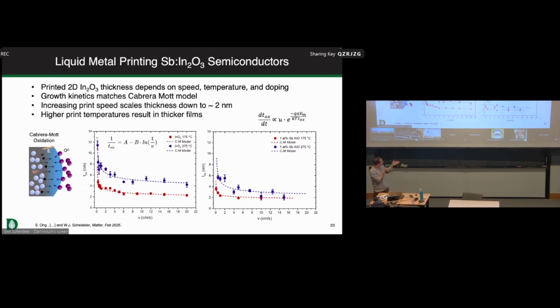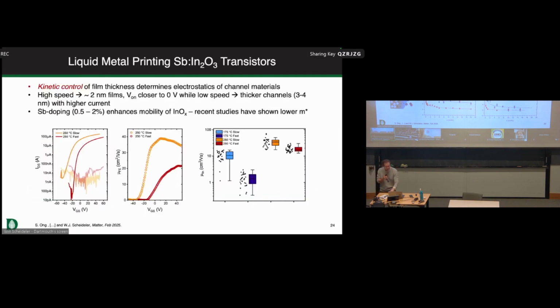So at the smallest scale, when we introduce a dopant like antimony, we can control it down to the 1 to 2 nanometer scale. Now, antimony is an interesting choice. It turns out that unlike a lot of other dopants like tin and gallium, antimony can actually enhance the mobility and lower the effective mass in the indium oxide. It has a little bit different influence on the band structure.